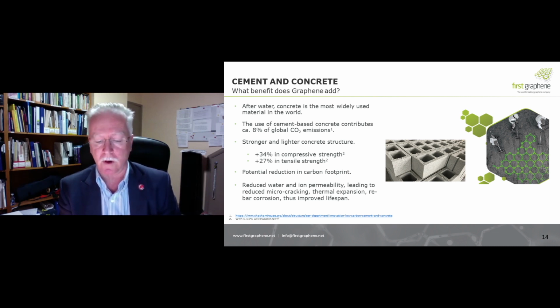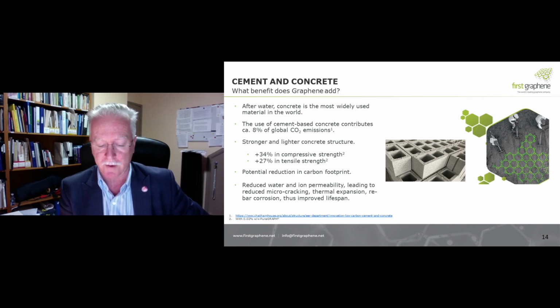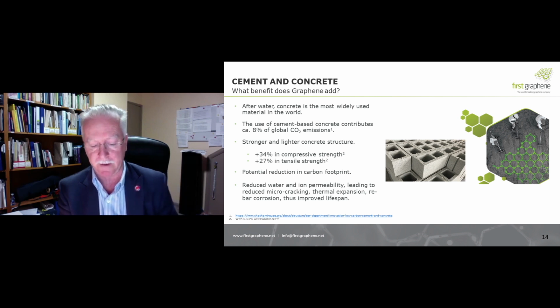Cement-based concrete contributes about 8% of global carbon emissions. This could be cut by a third with the addition of graphene. We've demonstrated that by adding just 0.8% of our pure graphene, we deliver a 34% improvement in compressive strength and a 27% improvement in tensile strength. The result is stronger and lighter concrete. Another benefit is the reduction of permeability by better than 50%.